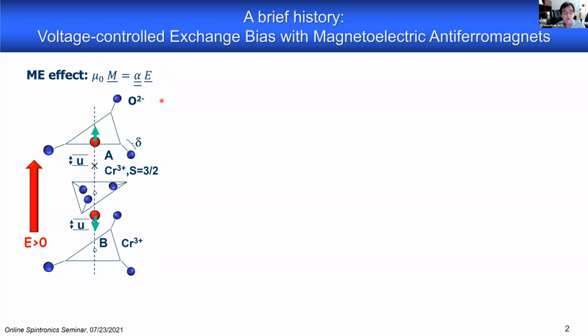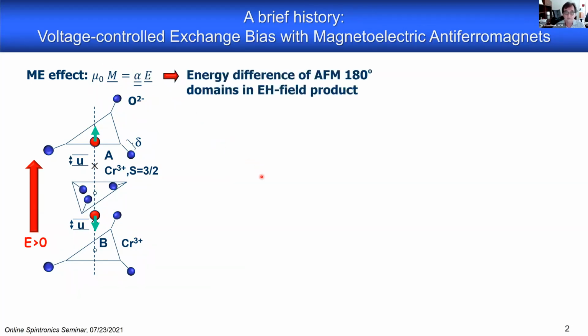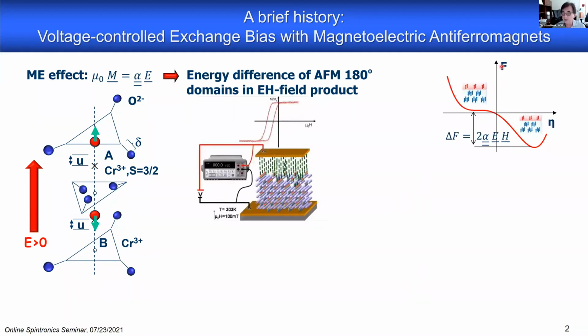That in turn means if you now take the system and put it into a magnetic field, then you create a Zeeman energy of that induced magnetization in the field. And there's a difference in the Zeeman energy between these two types of domains because the sign of alpha is different. And that is reflected here in this free energy landscape, free energy as a function of the antiferromagnetic order parameter. And you see here what happens to that formerly degenerate double well potential when you apply a product of electric and magnetic fields. You lift the degeneracy, and if you make that product big enough, then you can destabilize one type of single domain in favor of the other, so the system would switch over from one single domain state into the other.